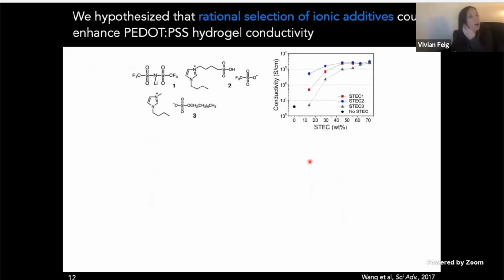And based on our group's knowledge of how to make and process PEDOT:PSS films, we hypothesized that if we could form PEDOT:PSS hydrogels with rationally selected ionic additives, then perhaps we could make much more electrically conductive gels as well. In particular, what our group has previously shown is that if you blend these ionic liquids with PEDOT:PSS and then spin coat them into films, you actually can observe really dramatic increases in conductivity.